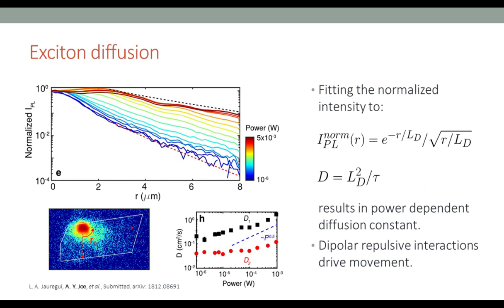What we find is that the diffusion constant seems to be changing with power. Normally when you think of a diffusion constant, it should not change with density, but in our case, since we have strongly interacting dipole moments, what we believe we're seeing is that as we increase the power, we're increasing the interaction between the interlayer excitons, which is driving the excitons further away from each other.